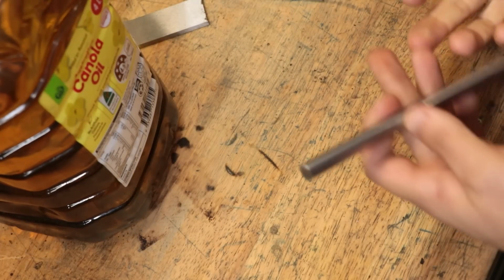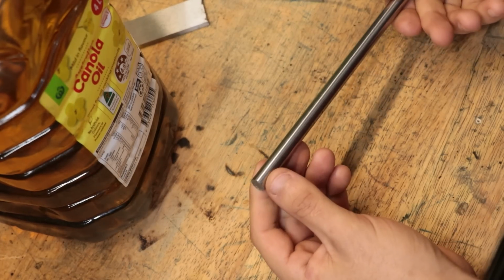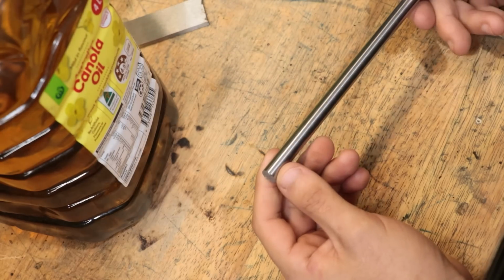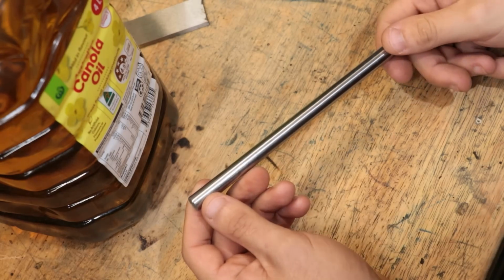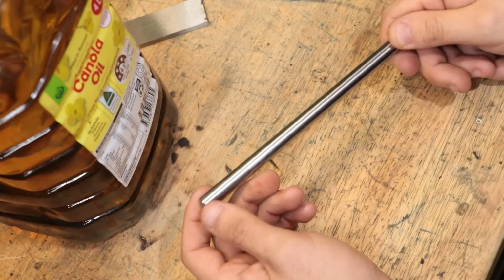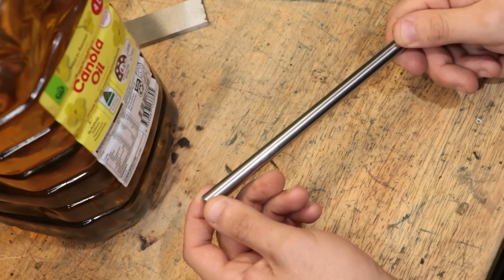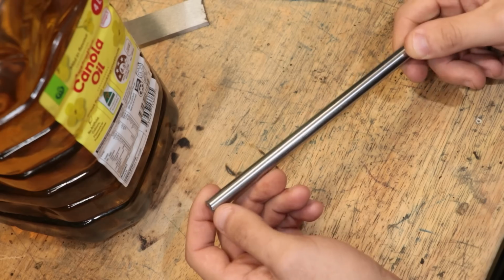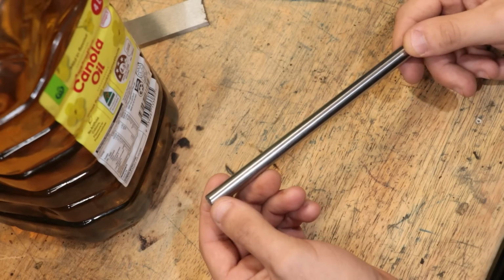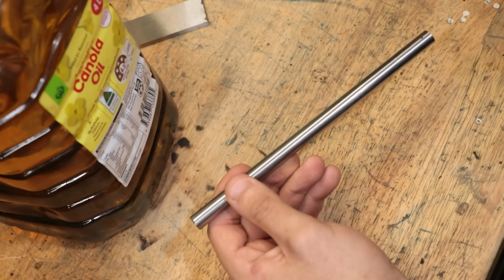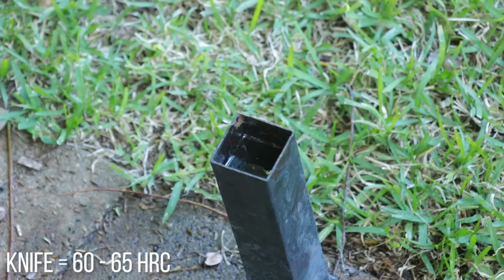Now, to get around that, I could quench it in oil, but the rate of cooling is about a third, so whilst the thermal shock is going to be less, the final hardness is also going to be reduced. And the amount that it is reduced is generally going to be determined by the oil, but also by the mass of the part. The smaller the part means the closer I can get to the max hardness that I could get with water cooling.